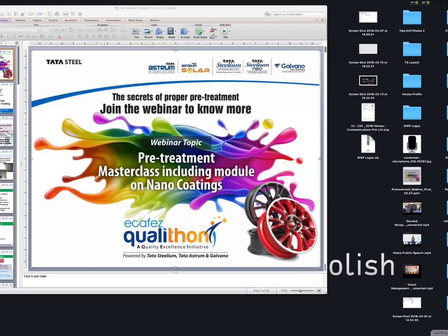There are certain methods of mechanical pretreatment where you can use emery sanding, or you can use hand tools, power tools, or sanding, or blasting, or ultra high pressure jet blasting. Or you choose the PO material, that is pickled and oiled HR material.